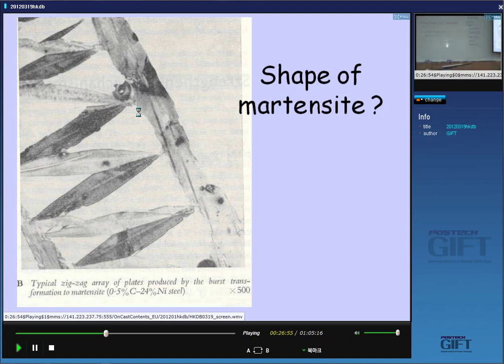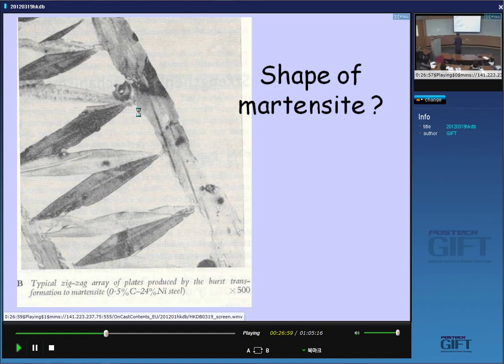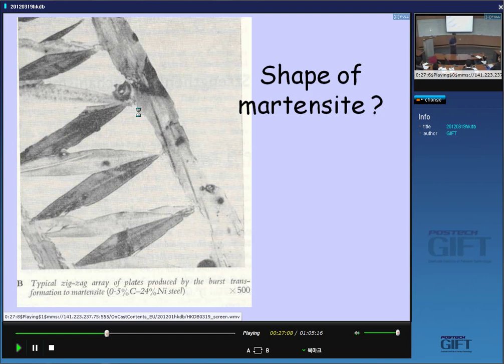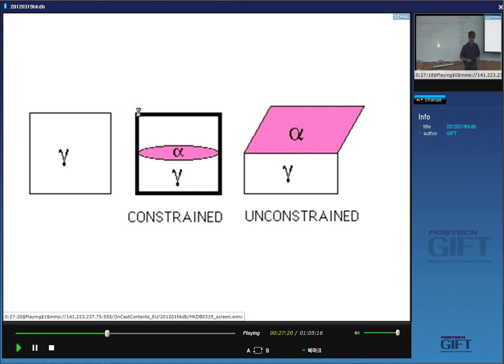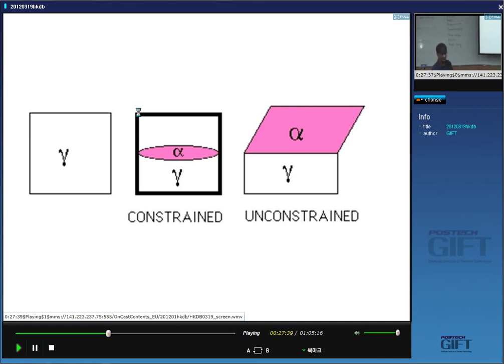I'm giving you all of these characteristics of martensite — we need to explain why we get all of them. Today's lecture is just summarizing what we need to explain; in the next lecture we will have the theory. The shape of martensite is in the form of thin plates or laths. When we get a change in crystal structure by a deformation, there will necessarily be a change in the shape of the austenite which transforms. This is a combination of a shear on this plane and also a volume change.